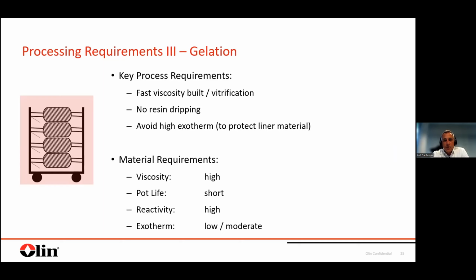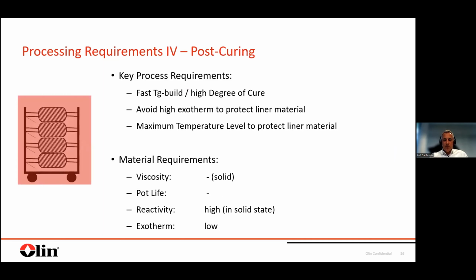You still do not want to see any resin dripping, and you want this viscosity build or vitrification to be as fast as possible. You can see from this fast viscosity build and avoidance of exotherm, there could be a bit of conflict. So viscosity in this step should be high. Pot life can be short, reactivity can be high, but still at a low to moderate exotherm. So again, it looks a little bit challenging to combine all these different requirements.